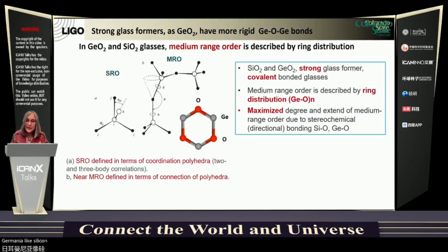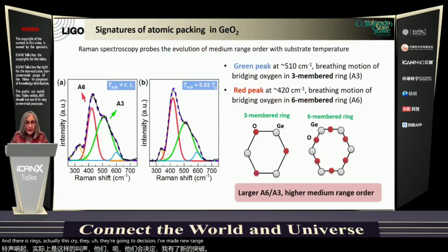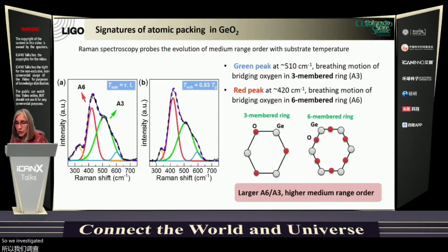Germania, like silica, is a strong glass former. So it organizes in tetrahedra that form rings, and I show here a 3-member ring. And these rings describe the organization at medium range. So we investigated the evolution in the medium range organization of germania using Raman spectroscopy. And you see here the Raman spectrum of germania that was deposited at room temperature, and another sample that was deposited near the glass transition temperature at 0.8 Tg, which is about 400 degrees C.